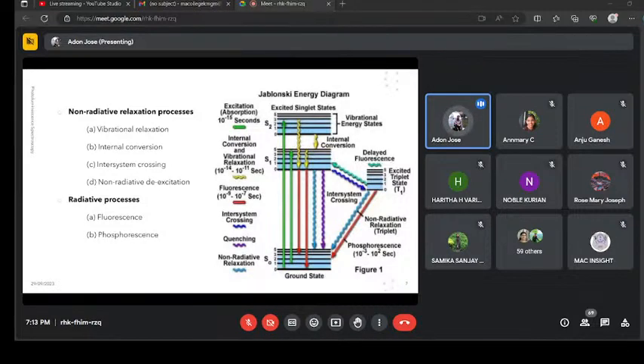We already defined that in the case of fluorescence, it is of the order of 10 raised to minus 8 seconds, whereas in the case of phosphorescence material, it is of the order of around 10 raised to minus 4 to 10 raised to minus 2 seconds. So based on this average lifetime of the excited states, we define whether the luminescence band is a fluorescence or a phosphorescence.